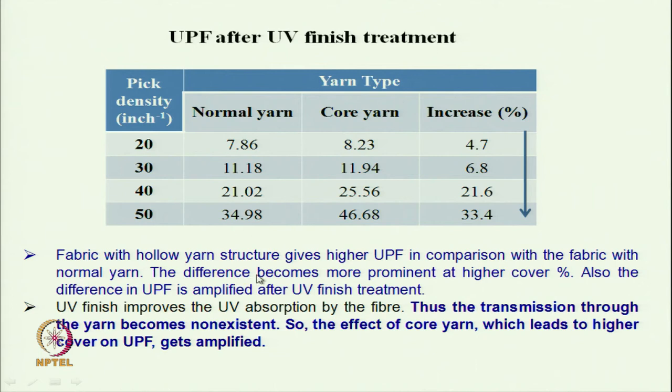Fabric with hollow yarn structure gives higher UPF in comparison with the fabric with normal yarn. The difference becomes more prominent at higher cover factor. Also, the difference in UPF is amplified after UV finish treatment. So, this is clear here, the difference is magnified.